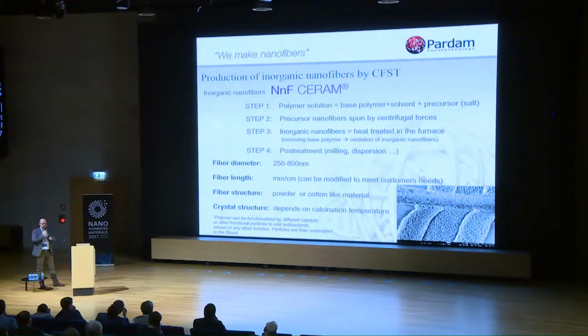The fiber diameters, I speak about nanofibers, but we rather have sub-micron fibers with very high surface area. So the fiber diameter is somewhere from 250 up to 800 nanometers. They are a little bit thicker than fibers made by electrospinning. The length is in millimeters or centimeters. We can mill it down to a few microns if customer requires so. Fiber structure is powder or cotton-like material, and the crystal structure and the surface area very much depend on final calcination temperature and on the calcination process.